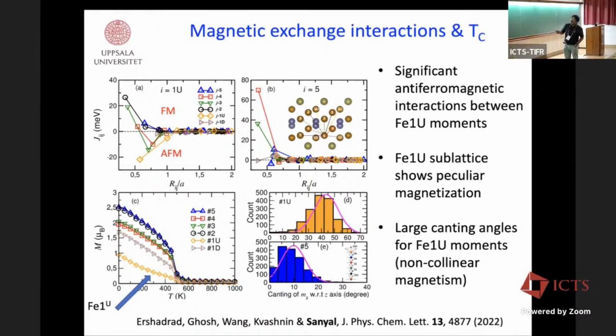specifically these orange ones, which are the antiferromagnetic exchange interactions in the plane of the iron 1 sublattice. So this is something that we are looking for, because we are looking for some frustration in the exchange interactions, where the simultaneous presence of ferromagnetism and antiferromagnetism is present. That's why these antiferromagnetic exchange interactions are very important for us. If you take another sublattice, I equal to 5, you would see mostly ferromagnetic interactions.